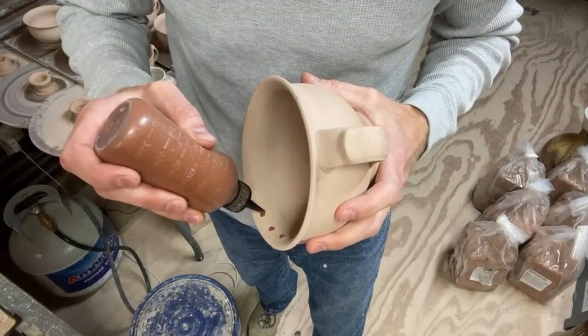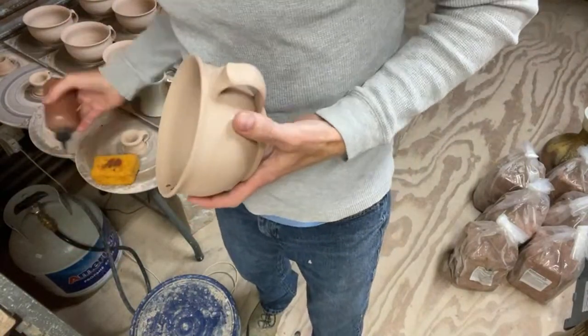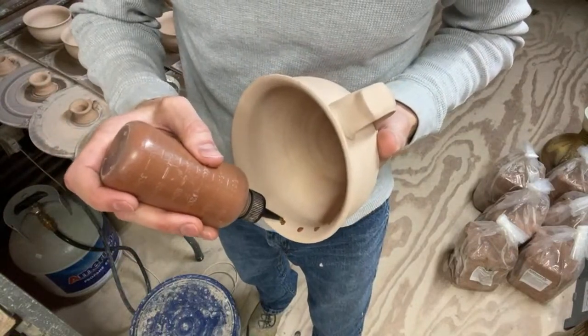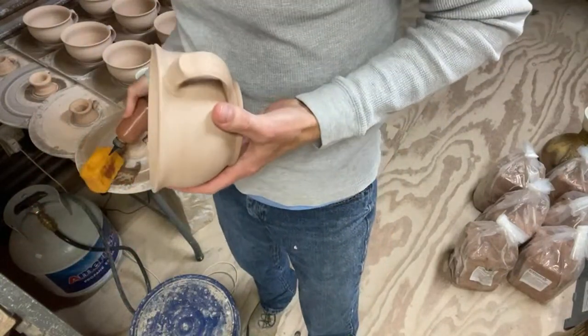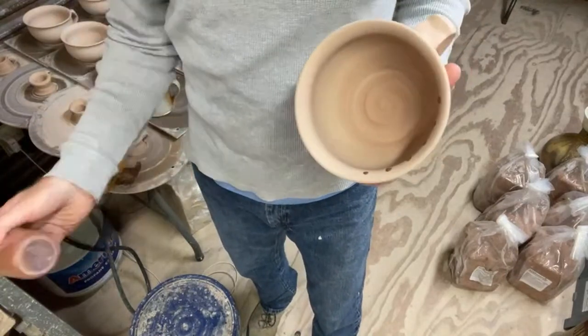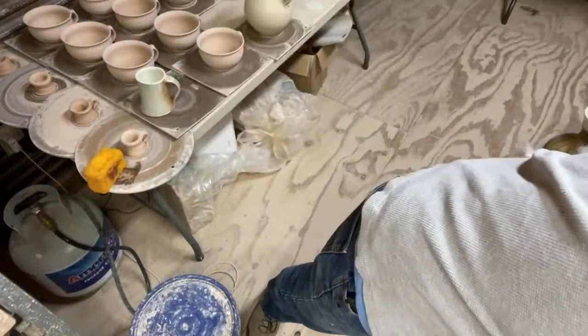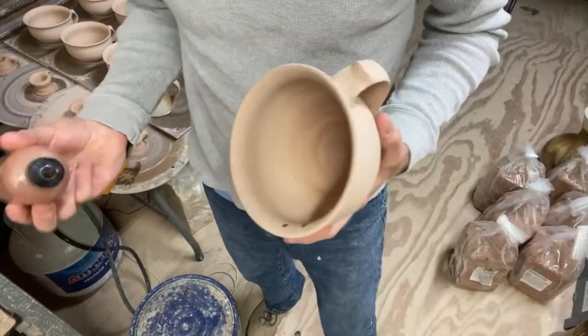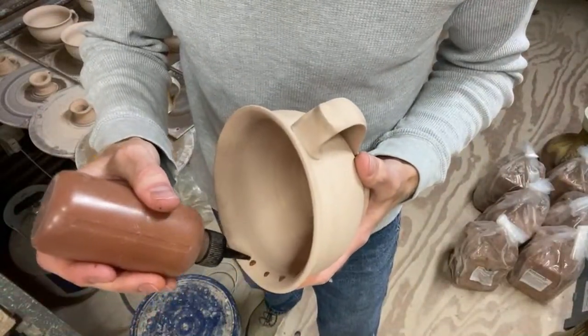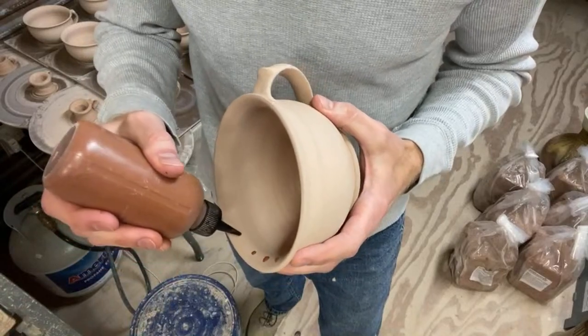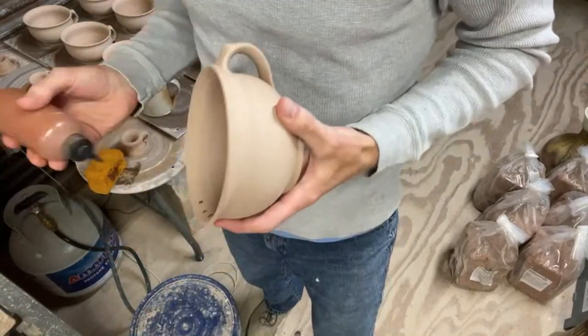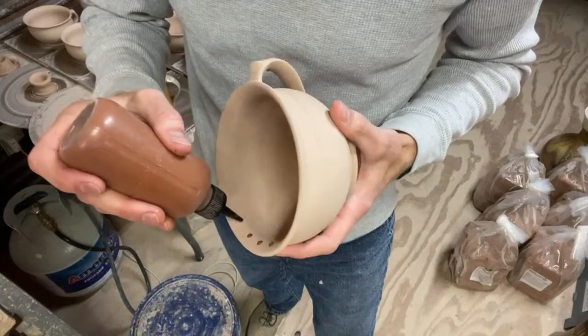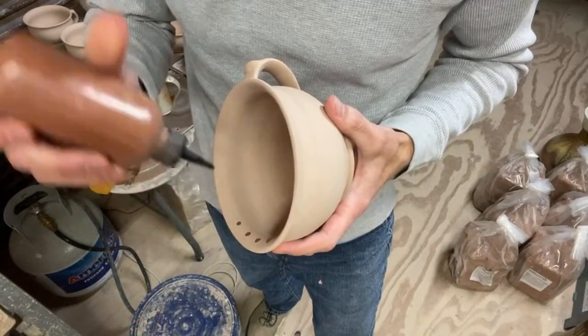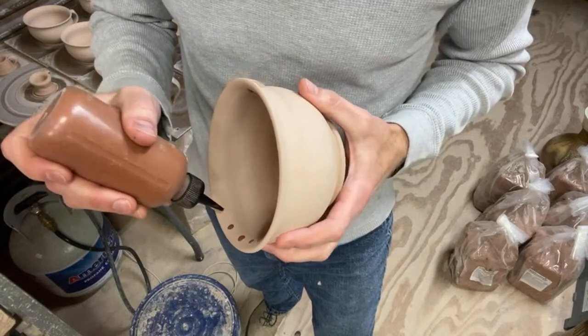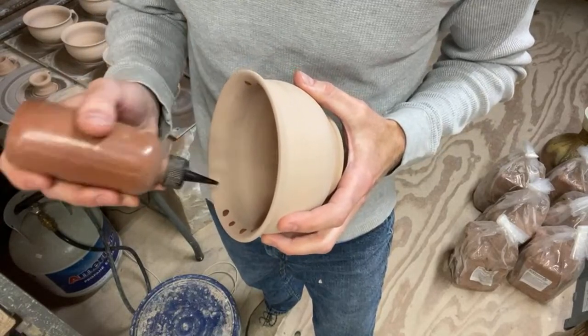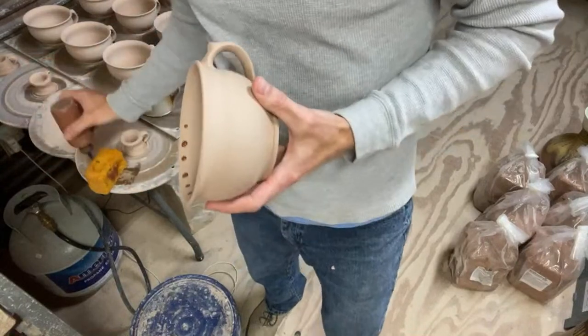This red one, recently I've been having problems with it. I probably need to sieve it a little better, because either the bottle's getting jammed up or the slip needs to be sieved better. If I squeeze it harder, it will come out fine, but then I'll make a mess if I'm only trying to do dots. With some slips, depending on the slip and the clay, you can't do this on dry greenware like this, but with this red slip, I know that I can get away with it. But I'm going to make a mess unless I get this working right.